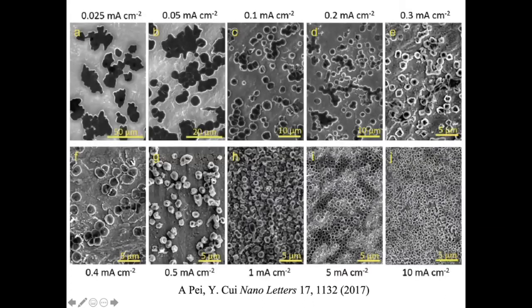A direct picture right here is showing you different current densities from left to right, top to bottom. You clearly see the radius of the lithium nuclei becomes a lot smaller with the current density. The number density is increased tremendously with current density, fitting nicely into the classical heterogeneous nucleation.